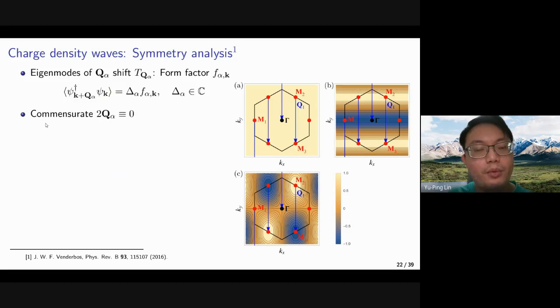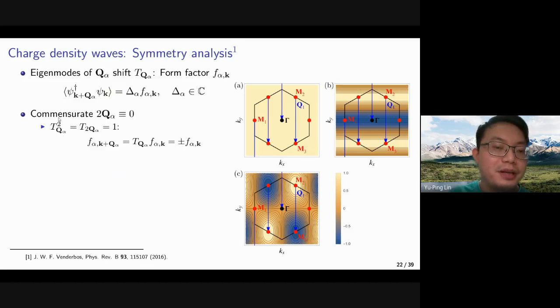So the commensurate condition is important here. The first thing to notice is that if we apply the T_Q twice, it will be equivalent to T_2Q. And because 2Q is just equivalent to the reciprocal lattice vector, we know that it should be a trivial operation. So the eigenvalue of the T_Q should be plus or minus 1. And the eigenmodes should transform into the opposite, or minus of itself, when we apply the T_Q.